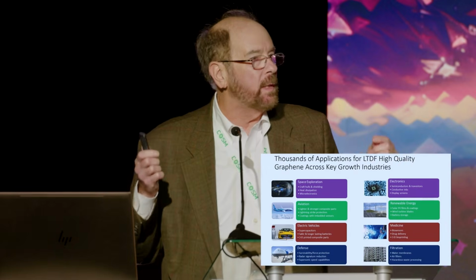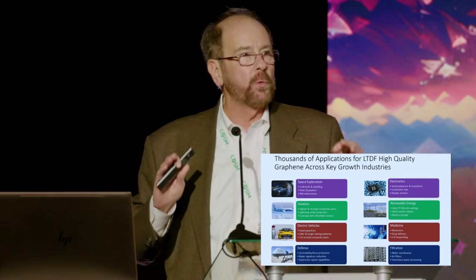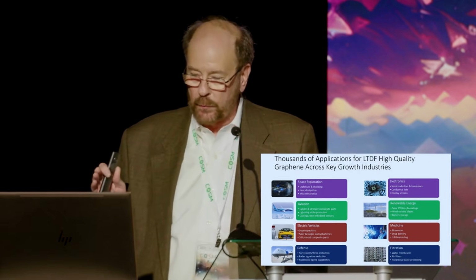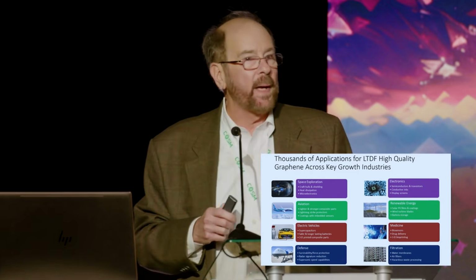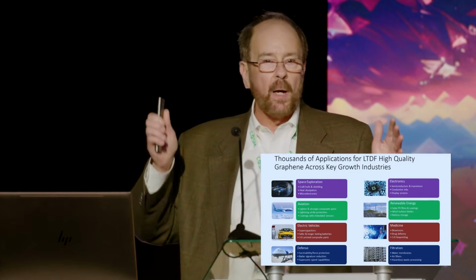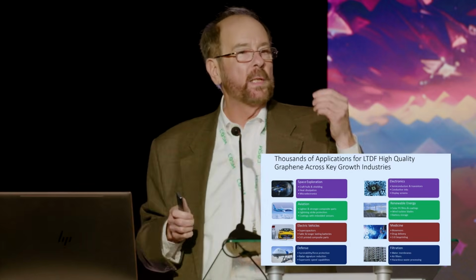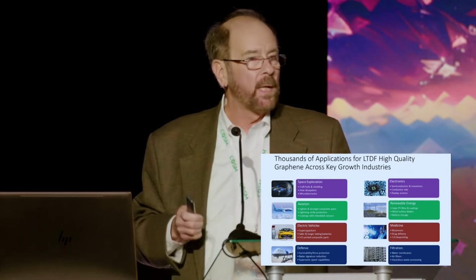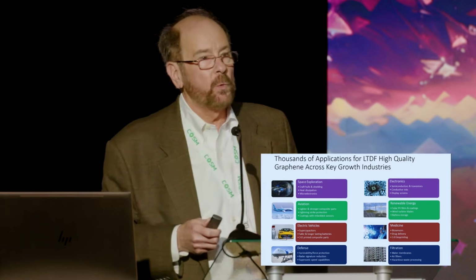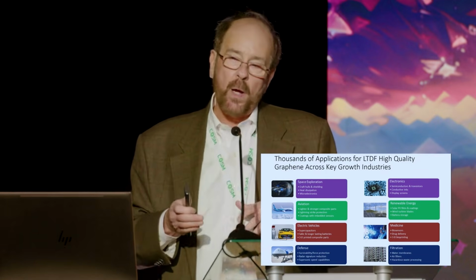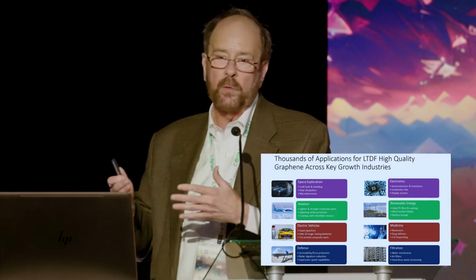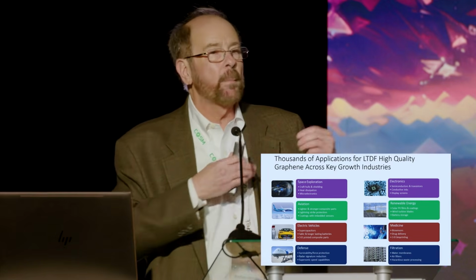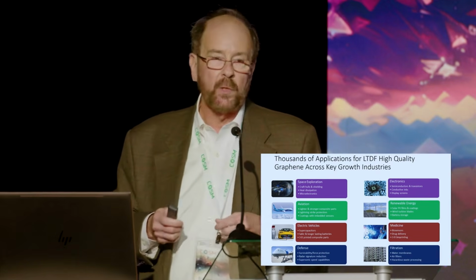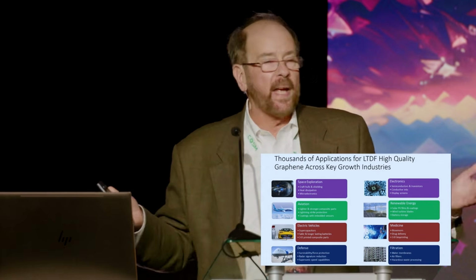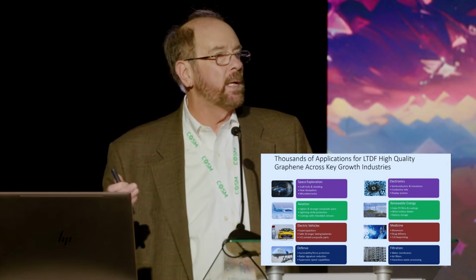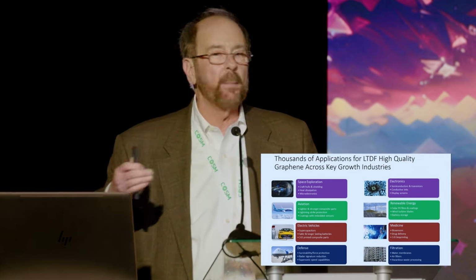For large, thin, and defect-free graphene flakes, there are literally thousands of high-value, high-tech uses. These are just a few of them. We are talking with NASA about using graphene to de-weight spacecraft, because obviously you have to put that weight into space. And if we can reduce the weight by 30%, a third, you can get more into space. We're talking about using graphene in electronics. Right now, electronics create a lot of heat. The heat is due to resistance. The resistance can be eliminated to a very great degree by using graphene instead of copper for electrical interconnects. Aviation, Richard Branson is well known for the last several years trying to champion using graphene to reduce the weight of commercial aircraft by maybe a third.